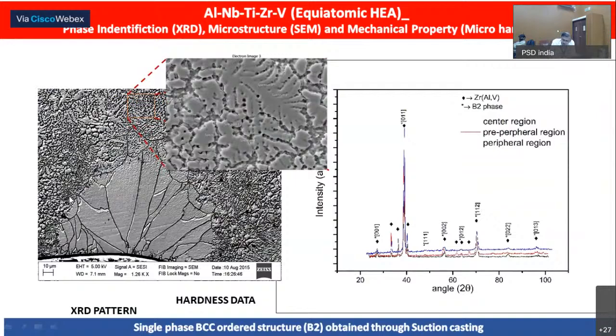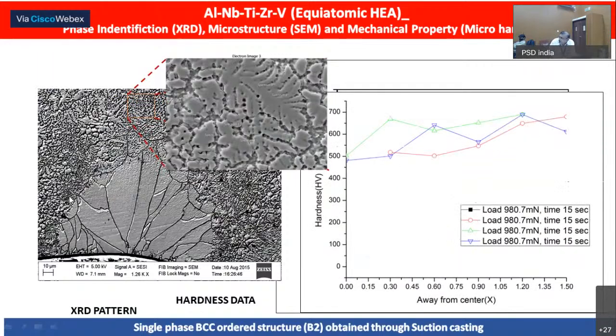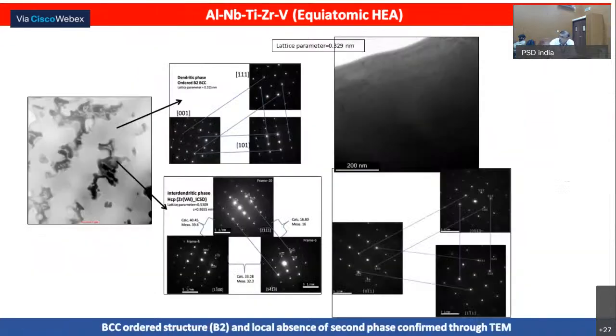These two phases are the BCC and B2 structures. When hardness was measured, you can see the materials are really, really hard. To put it in the right perspective, a typical steel hardness is close to 300, so they are nearly twice as hard as conventional steel. I'm talking about high strength steel.